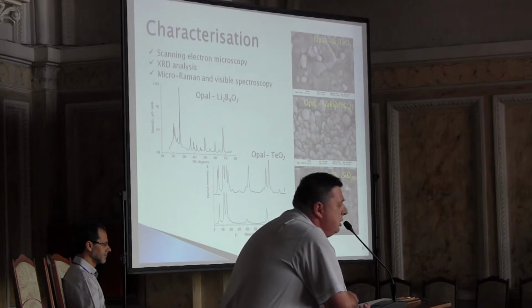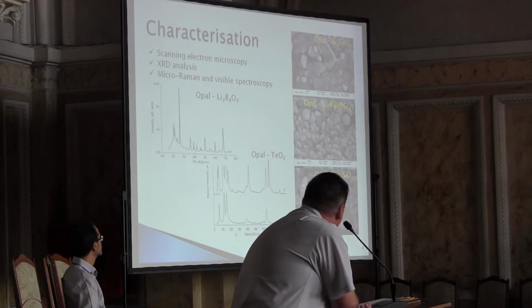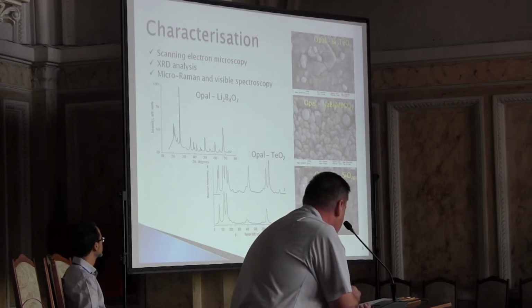In the case of the melt-based technique, the filling degree is up to 60% or more, in contrast to the previous solution-based technique, when for the first cycle of impregnation we have less than 10%. Well, these micrographs.